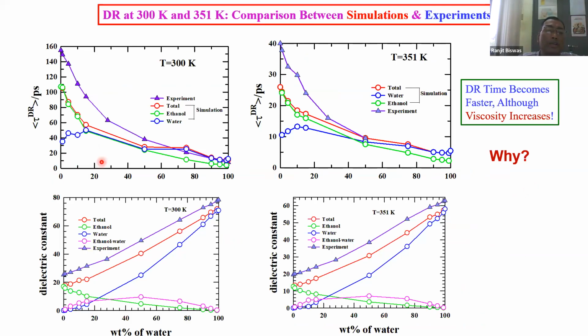And this is a comparison between experiments and simulations. You see, this is 300 Kelvin, this is 351 Kelvin. So the left panels are all room temperature data, and the right panel is 351, that's the azeotropic temperature. And this is very interesting. This time constant is also decreasing as we increase the water content. What exactly are we thinking of, why is it happening? And this is pretty general, even at 351, although the numbers are faster, the time constants smaller, the composition dependence is very similar.